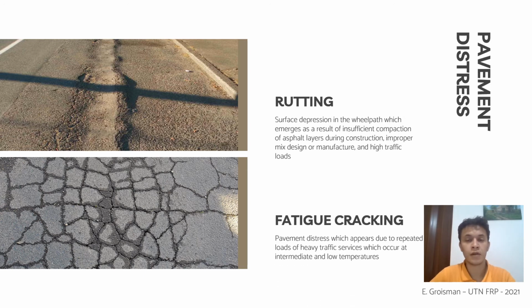And now the fatigue cracking, which is a pavement distress which appears due to repeated loads of traffic which occur at intermediate and low temperatures. What happens here? As the number of loads increases, longitudinal cracks begin to appear, and as we continue increasing the amount of loads and traffic, they start to connect between them, forming what we can see in the second picture, which resembles the back of an alligator or a crocodile. That's why fatigue cracking is also known as alligator cracking.